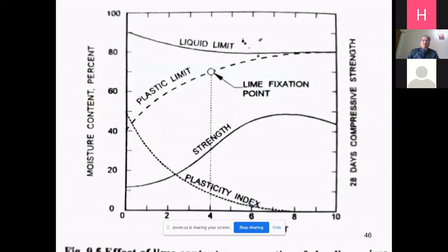But if you want to know the actual requirement of the lime, then you have to go for this. This is showing the moisture content on one side, and here it is showing the percentage of lime. You can see the liquid limit is coming down, and the plastic limit is going up. So basically the PI is the difference of these two. Since the difference is decreasing, the plasticity index is coming down. Similarly, strength is going like this. Strength is maximum here, but at that point of maximum strength, the requirement of lime is very high. It is more than 7%, which is not needed, and it will be very costly also.